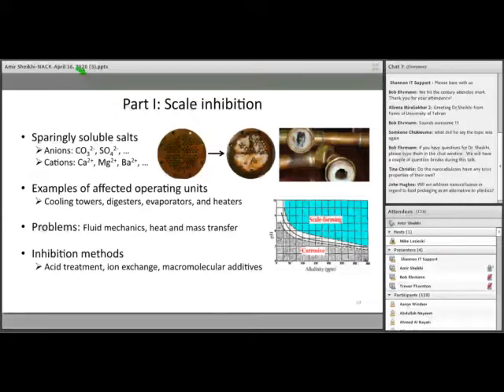Okay, let's continue with the first challenge that we are going to discuss: scale formation. What is a scale and a scaling? Scaling is the formation of sparingly soluble salts, such as the salts of carbonate and sulfate with calcium, magnesium, and barium, which tend to adhere to unit operations such as cooling towers, evaporators, digesters, pipes, heat exchangers, and so forth, as you can see here, which increase the resistance against the heat, mass, and momentum transfers. They impose serious challenges to water-based industries. These are operational and economical challenges.